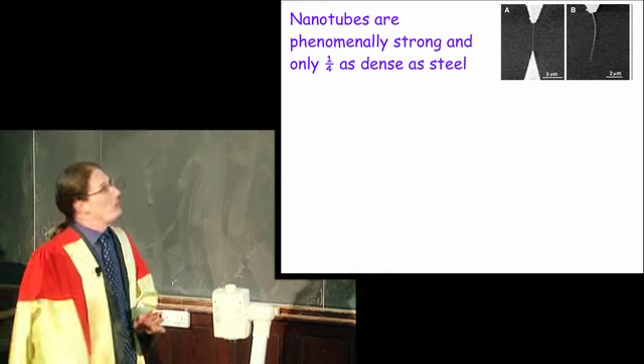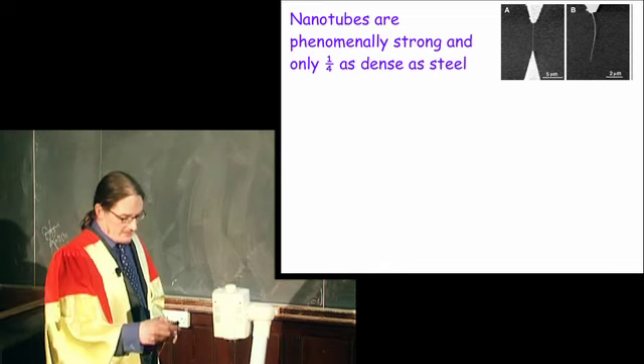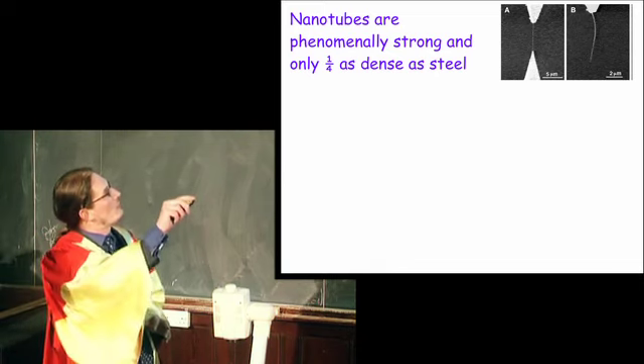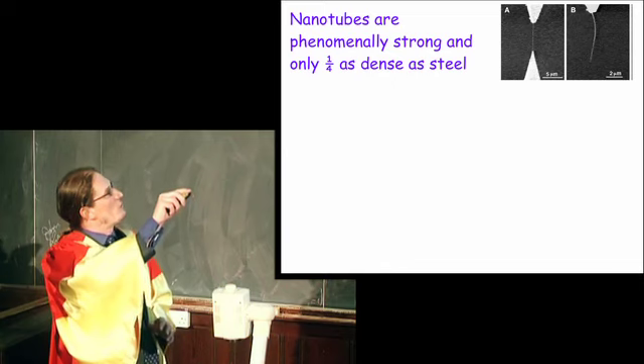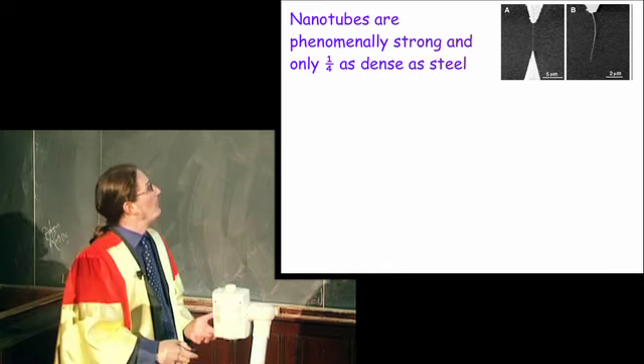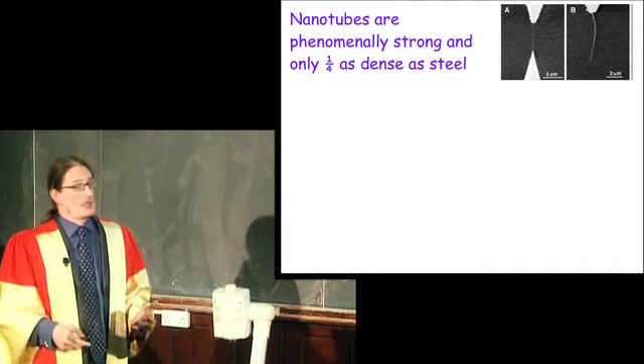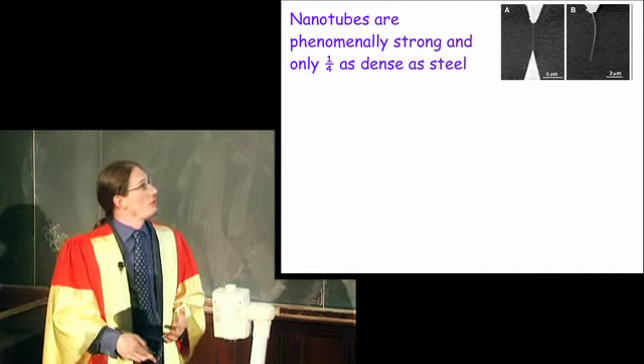The other thing that's very, very useful about them is that experiments about 10 years ago where people were able to grab onto carbon nanotubes in an electron microscope and pull and break them showed that they're phenomenally strong, yet only about a quarter as dense as steel.